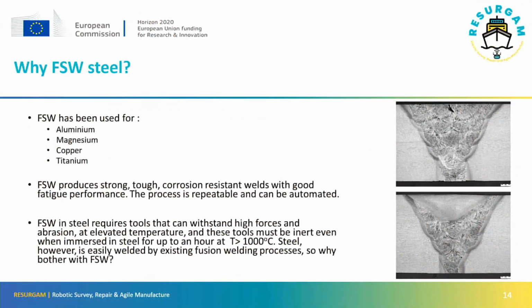So in these pictures, what you see in the upper image is a typical multi-pass arc weld in 20mm thick steel. So you've taken the fine-grained wrought plate, passed an arc welding tool through it up to 20 times, and converted that microstructure to a cast microstructure. So you've probably got shrinkage defects there, you've got a large heat affected zone, you've got columnar grains. It is not as strong as the original parent material. In the lower image, what we've done, we've passed a friction stir welding tool through the surface of that weld.